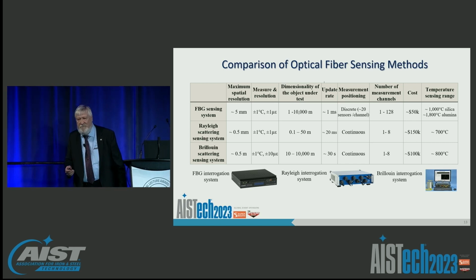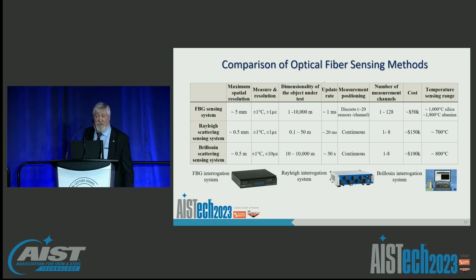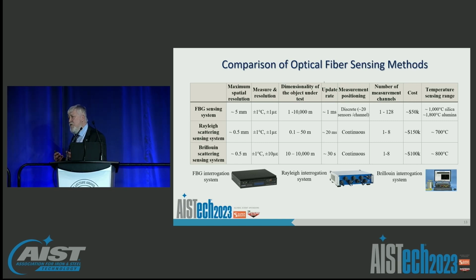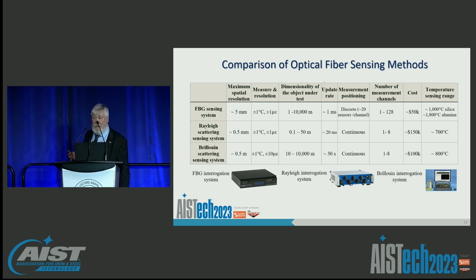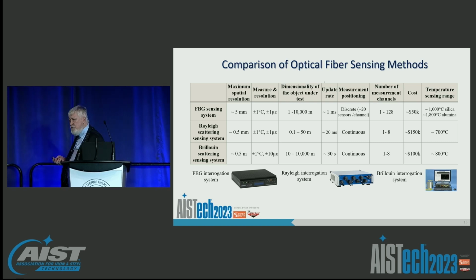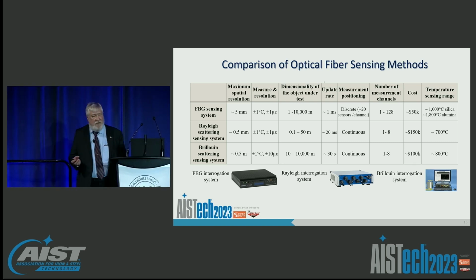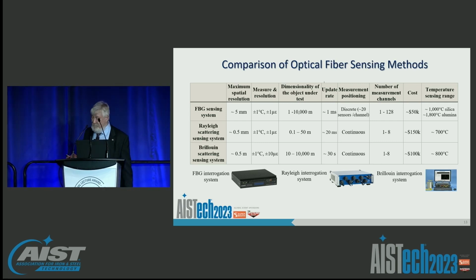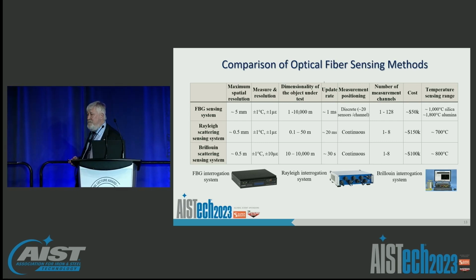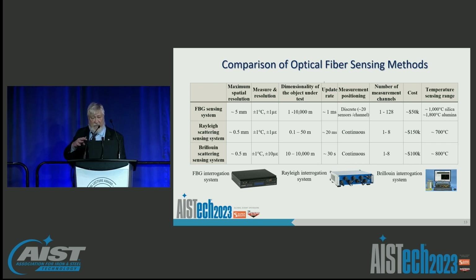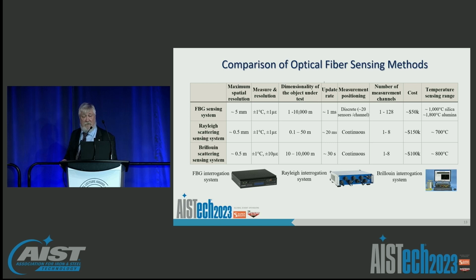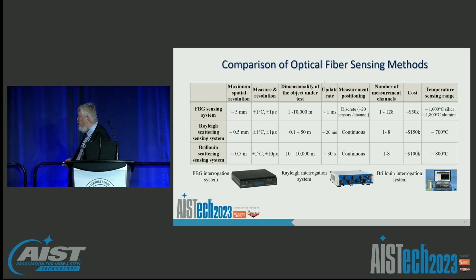So there's also other measurement methods, Brillouin scattering, which is a method like Rayleigh scattering, except the scattering is in a different frequency domain and essentially initiated by different origins in the reflection spectrum. But those typically have a much lower resolution, on the order of 0.5 meter, but they can continuously measure over, again, tens of kilometers of length. So this just shows some of the comparisons of the ability to the number of channels and the cost of the systems and so forth, and you get some feel for what the temperature capabilities of each of these are.